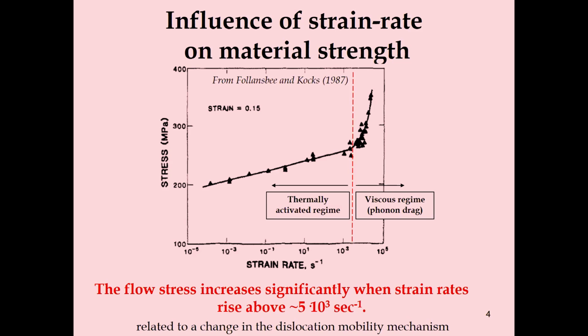As we're looking at in the low regime at thermally activated dislocations, as we go higher, we're getting the effects of phonon drag, and the oscillations of the atoms are now interacting with the mobility of dislocations.